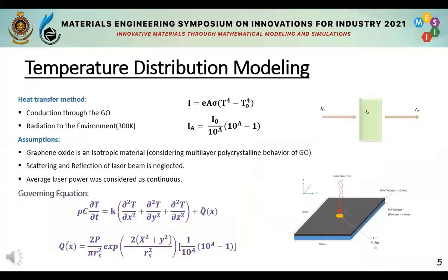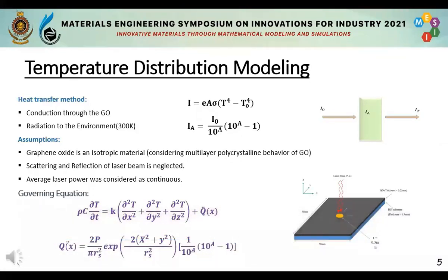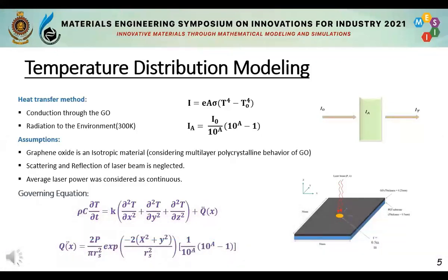As the next step of our project, we did temperature distribution modeling. We considered that heat transfer happened according to two methods: conduction through the graphene oxide layer, and radiation to the environment. Here we made several assumptions. First, graphene oxide is an isotropic material. This was assumed considering the multilayer polycrystalline behavior of graphene oxide. Then we assumed scattering and reflection of the laser beam is neglected, and average laser power was considered as continuous. By using heat conduction equations and considering non-steady state, the governing equation was derived, which is shown in the slide. Then for the three-dimensional temperature distribution of the graphene oxide film, we used COMSOL Multiphysics software for modeling purposes.